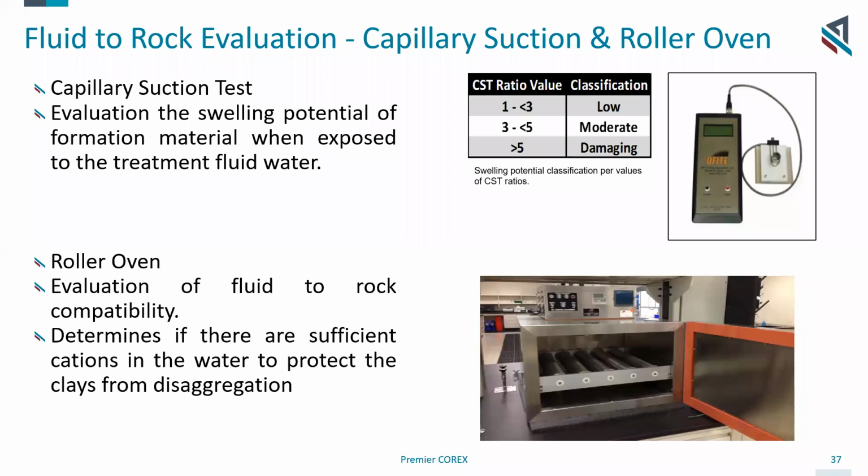Some other tests which are used with cuttings is the capillary suction test, which basically, the higher the clay content, the greater the interaction between the formation material and fresh water, which is expressed in the longer the capillary suction test time takes, and gives us an evaluation of the swelling potential of the formation when exposed to different treatments.